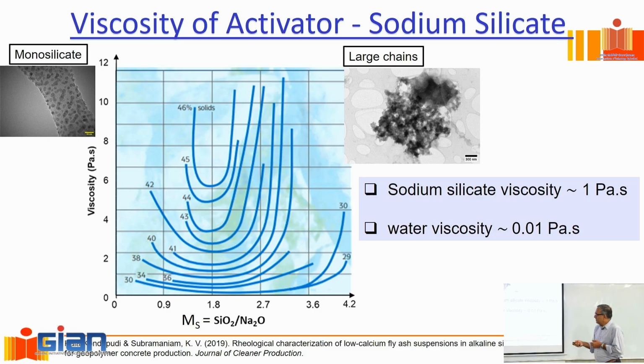Initially, you start with a lot of monomers. This is a TEM image of silica with a very low MS, so you get a lot of individual particles. So why does the viscosity decrease? At some point, these particles start coming together and forming dimers, so the volume of space that they occupy within the liquid starts decreasing. So what you see is the viscosity decreases, hits a minimum and then shoots off. When it starts shooting off, that means it's starting to polymerize.